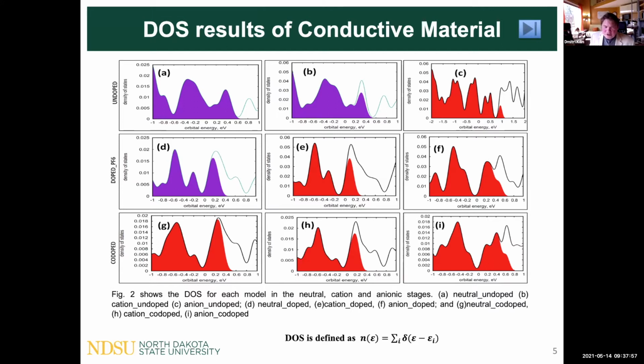Does it satisfy your question, or do you need more explanations? I think that's fine. I mean, the main point here is it seems to have a small band gap, but during the calculation there are broadening effects. You have to use either a Fermi function or a delta function with a finite width, right? And if the parameter is quite large, you get overlap. Exactly. And it's just an artifact from the calculation. Exactly, and it makes a deceptive impression on the graph.